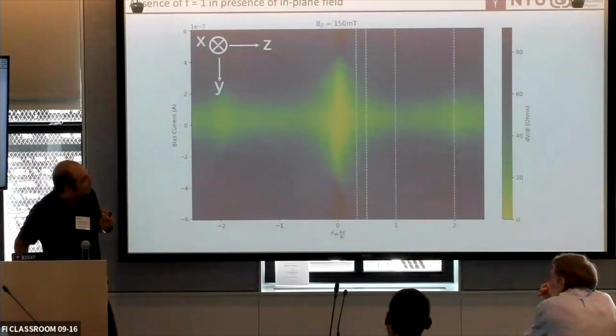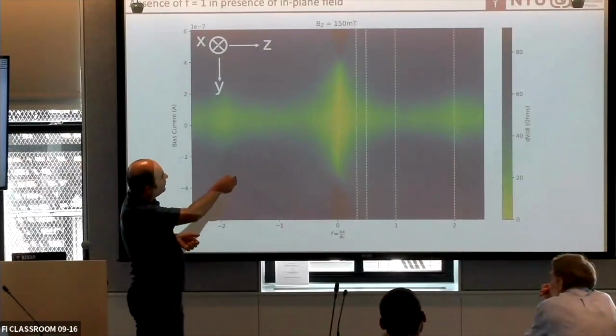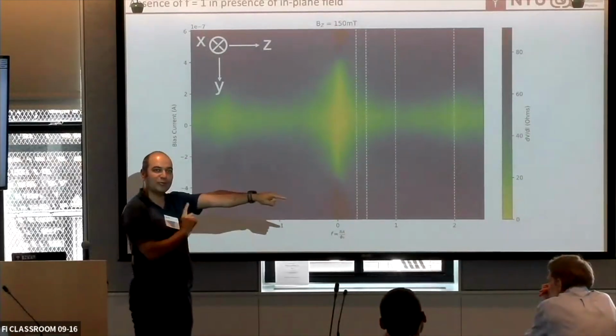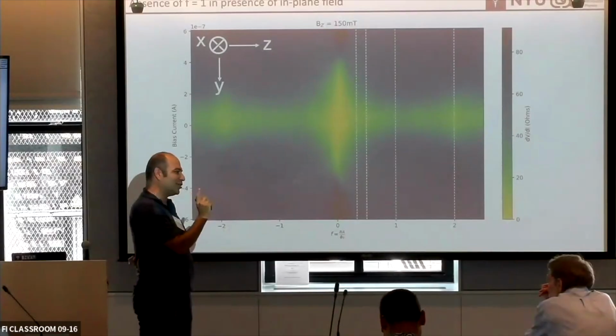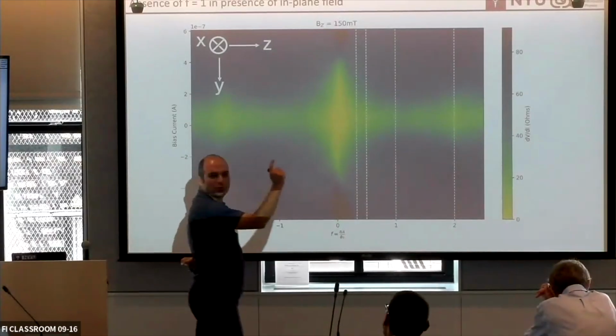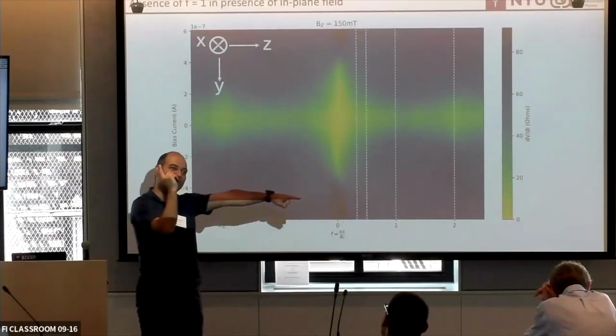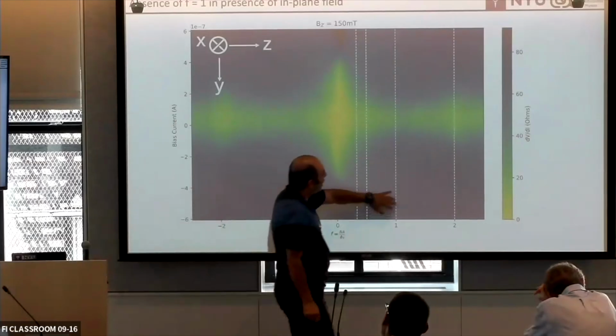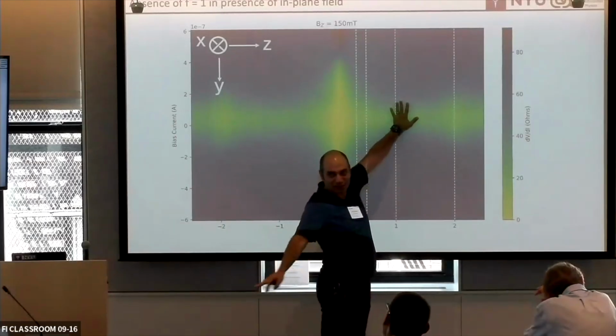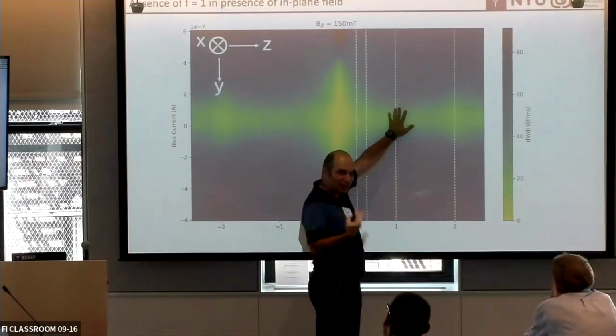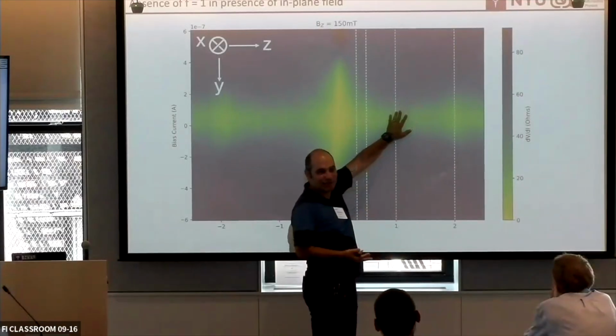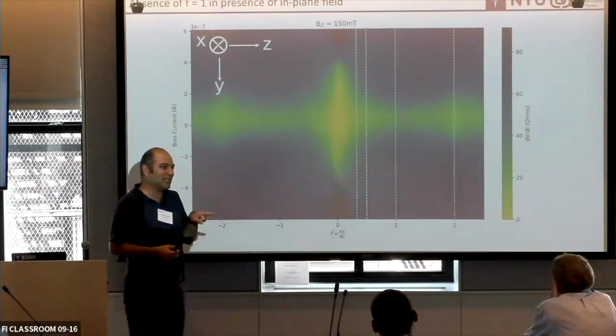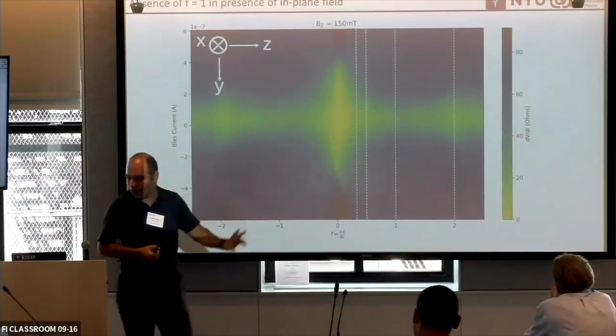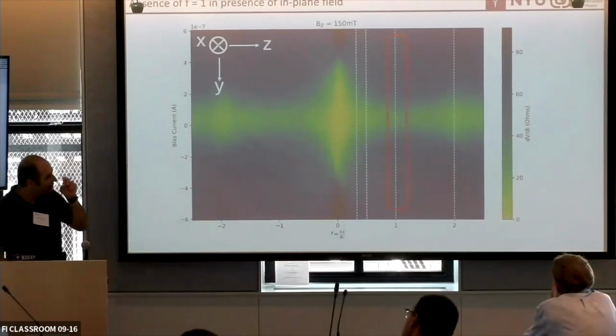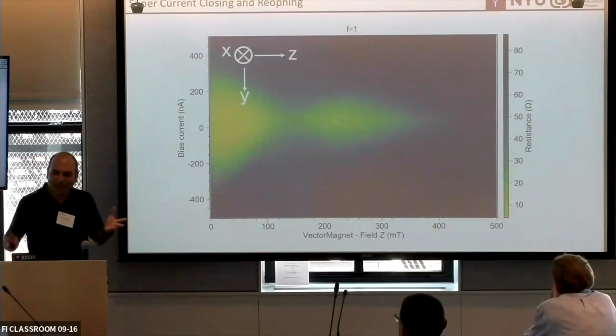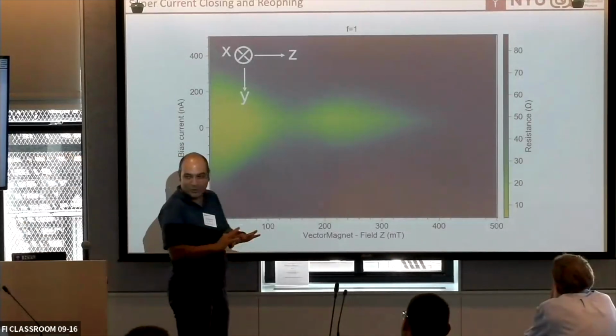So we said, okay, if I apply 150 millitesla in the plane and look at the filling factors again: at 0 in-plane field, I see 1, 2, all of that. Now I put in 150 millitesla, and I don't see 1 at all. 1 is gone. 1 is not a good number anymore, which was supposed to be one of the strongest phases, one that is hard to destabilize. We put in a little bit of an in-plane field, and 1 is completely gone. And then you can ask, well, wait, what happened? Why 150 millitesla? Show me the whole graph, right?